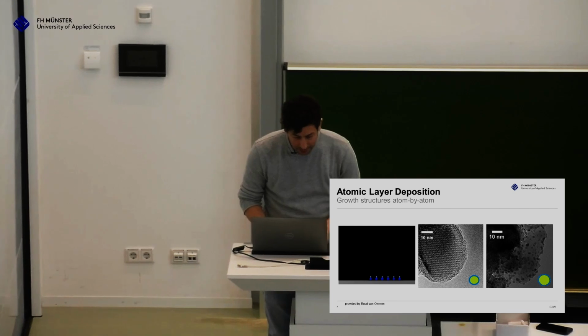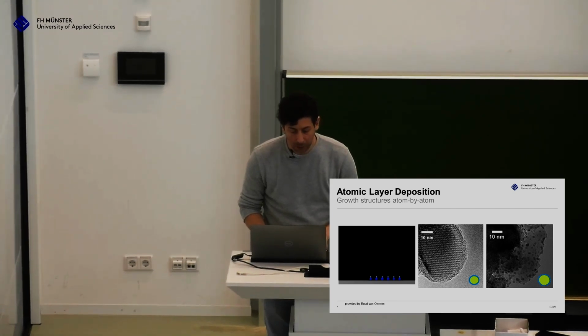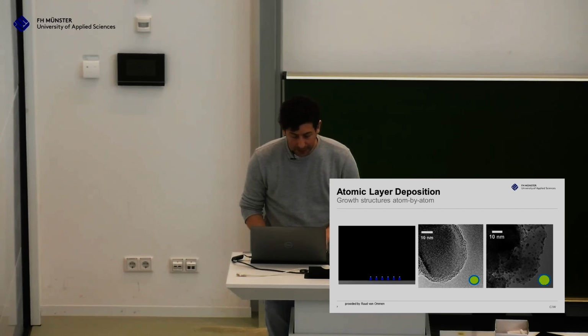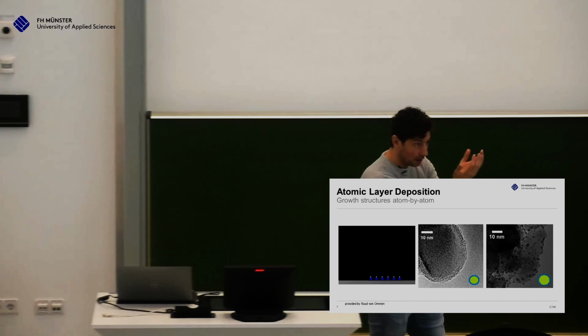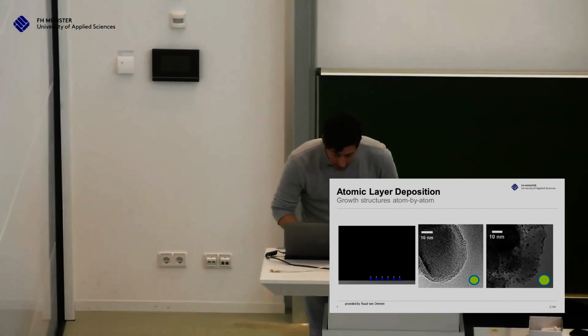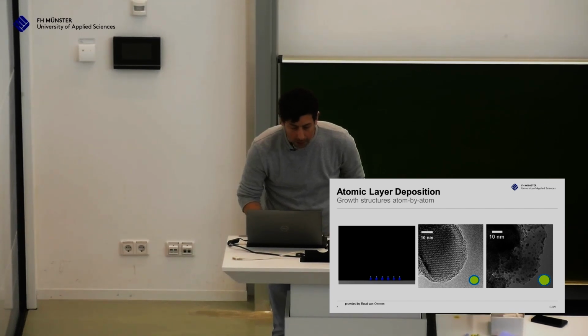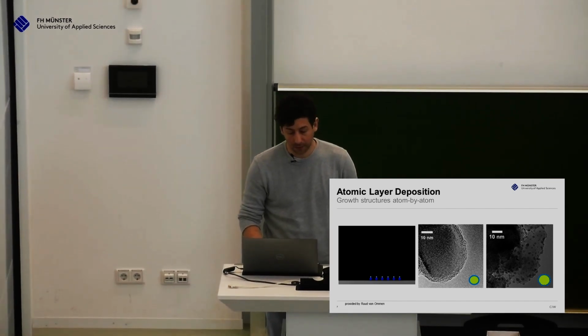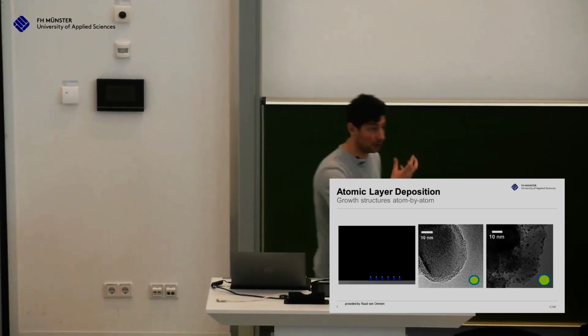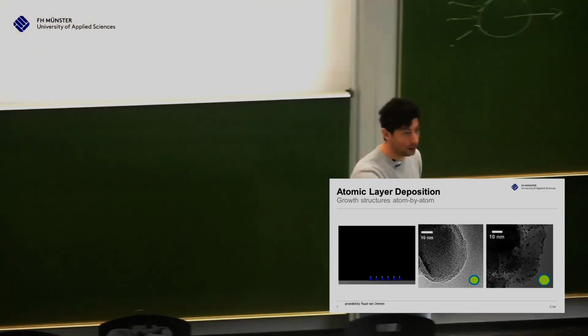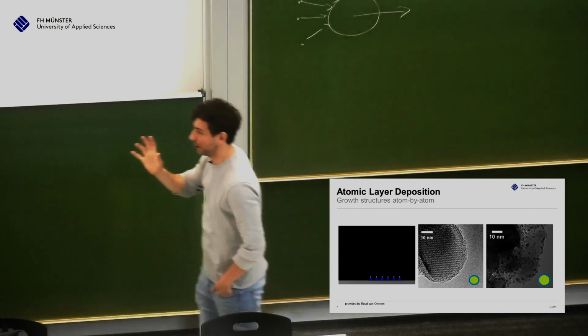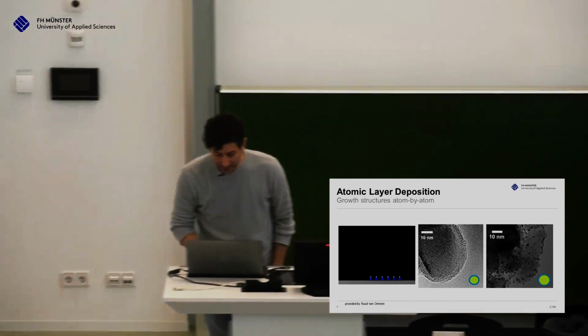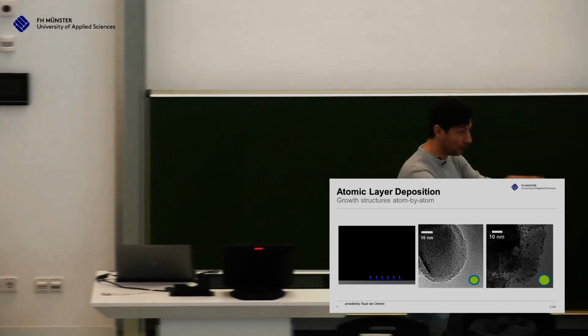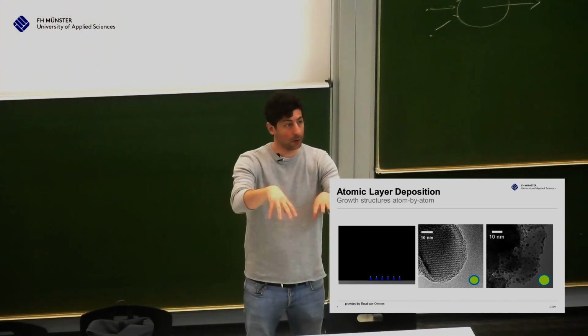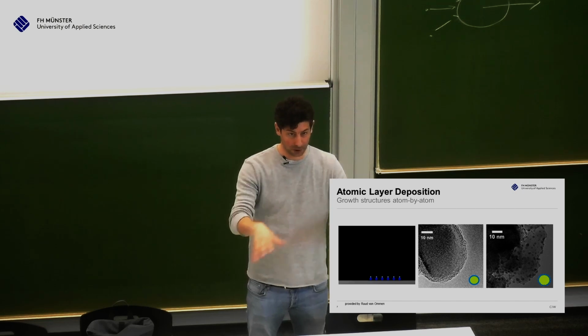So here we have titania, and these are titania nanoparticles, and they are surrounded with an aluminum oxide layer. And this aluminum oxide layer is just a safeguard, okay? And you see here the crystalline structure of the core particle, and you see the amorphous structure of the atomic layer deposition around it, okay? It's just a few layers of atoms. And here we see another one, and this is called island growth. This is for catalysts. In a catalyst, you need very high surface area. So you need small particles, and nanoparticles are small, right? 10, 20 nanometer. But these islands here are copper islands, and they are in the size of 1 nanometer. So much better, but you need a carrier for them. So you have a carrier where these islands can grow, and then you have an extremely good and cheap catalyst, because you don't need much material.